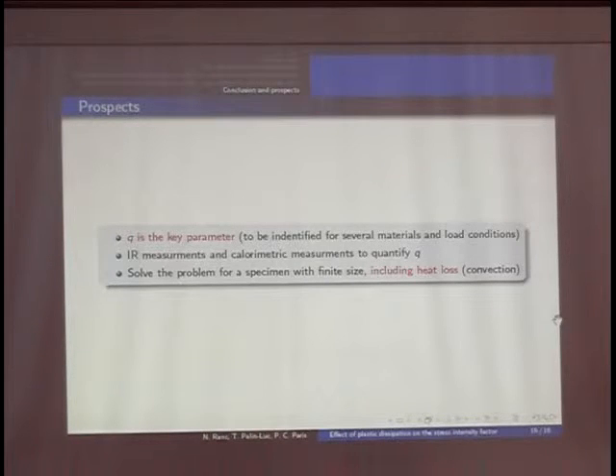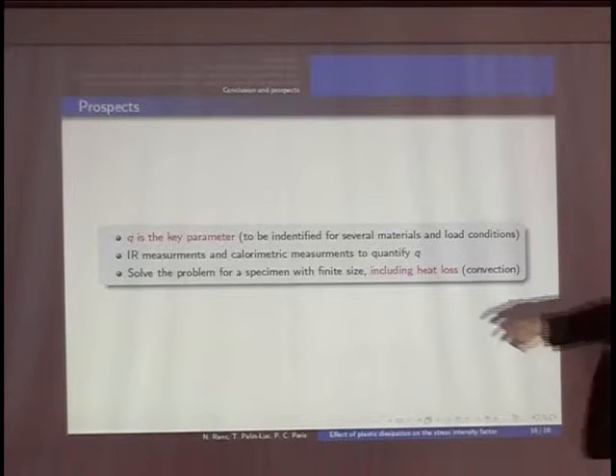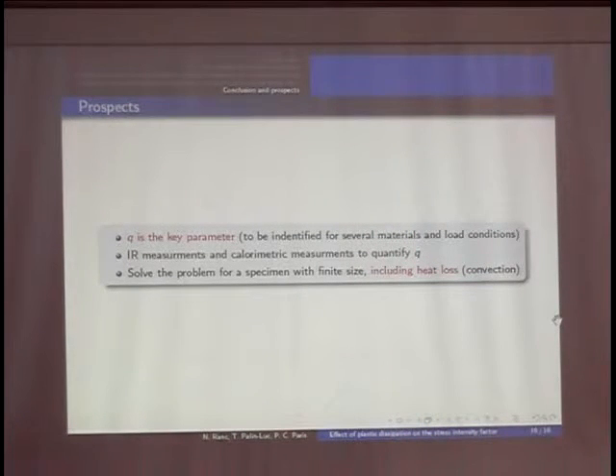But I think that an important point also is, as it's written here, Q. I don't know what is the Q value, for instance, when you are at very high strain rate, because I guess that the mechanical cyclic behavior of the material, for instance, if there is viscoplasticity, will affect the value of Q. Usually we estimate this value by experiments with classic frequency between 1 and 100 Hz. But I don't know what happens if you multiply the frequency by 100. But it's very important.